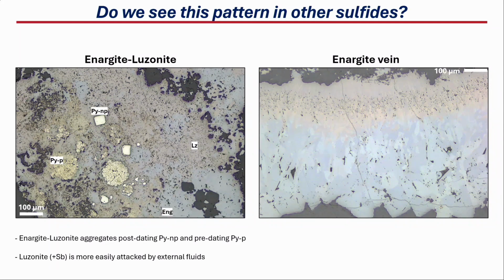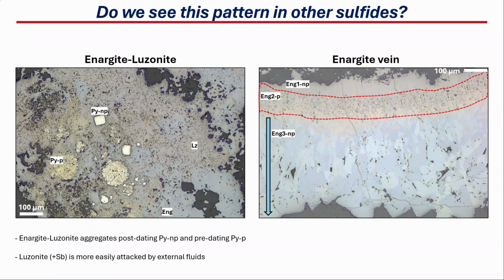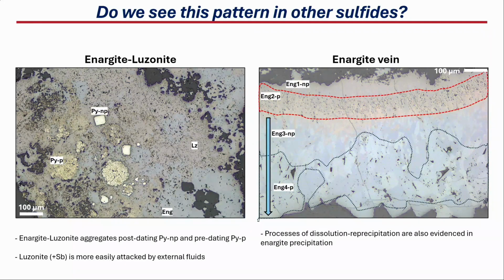Another example is an enargite vein that actually can recall all the different processes. So we see differences in textures throughout this vein, starting from a first generation of enargite, which is non-porous. Then we have another generation, which is porous. We have overgrowth of enargite, and again, some porosity. So what it's essentially showing is that we can evidence dissolution, reprecipitation processes and the cyclicity in enargite as well.